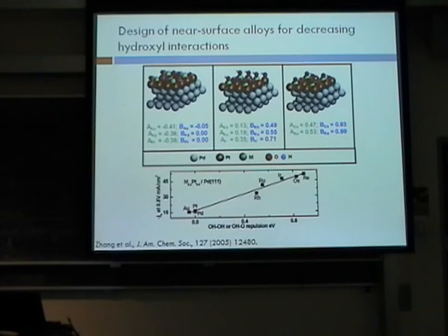that will come to the surface. And sort of counterintuitively, they've chosen metals that bind hydroxyls very strongly. It turns out that this can be a good thing because the hydroxyls that are bound on this second metal, which is shown in green, will tend to repel hydroxyls that would accumulate on the platinum atoms that are really doing the work of the reaction. So by having hydroxyls on the inactive part, you disfavor a lot of accumulation of hydroxyls on the active part of the catalyst, which is the platinum.